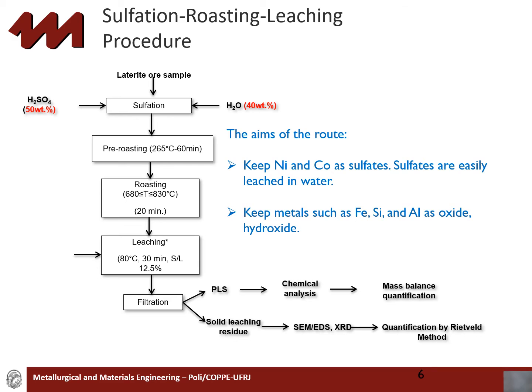The sulfation roasting leaching basically consists of sulfating the ore sample with concentrated sulfuric acid at room temperature plus water. The sulfated sample is subjected to heat treatments at temperatures ranging from 200 to 700 degrees in one or more stages. In this case, it was done in two stages. The first one, called pre-roasting, was done at 265 degrees Celsius for 60 minutes, and the second heat treatment, called roasting, was done in the temperature range from 680 to 830 degrees for 20 minutes.